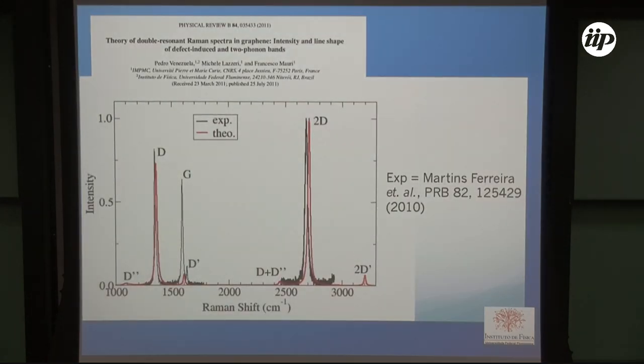Then we compare our calculations with measurements. This is the measurements by the Inmetro group in Rio de Janeiro. The first author is Erlon Martins Ferreira. And first, we don't have the G band, because the G band is not a second order process. So we didn't calculate it in this paper. We calculate all the double resonant processes.